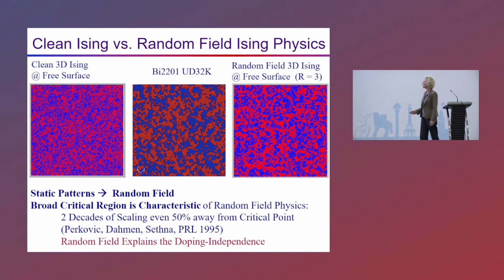So the very large critical region of the random field model explains the doping independence that we saw. The prediction would be, give us larger fields of view, and then we should be able to detect the correlation length, and it should be a function of doping. So I would love to have much larger fields of view. I think we will have to go to a different probe because STM experimentalists don't want to give me 100 times the dynamic range here. Okay, thanks.